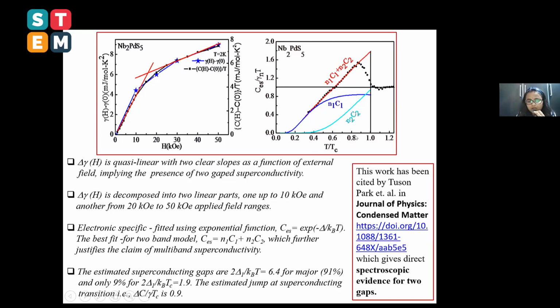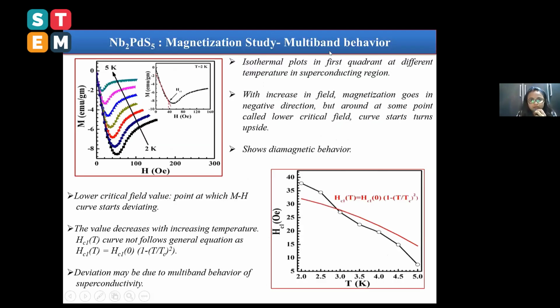And this work has been cited after this study. This work has been cited by Tuson Park et al. in the Journal of Physics: Condensed Matter. In this paper, they gave direct spectroscopic evidence for two-gap superconductivity. After this study as well, Nb2PdS5 fibers were grown by several groups, and they also showed from anisotropic measurements that Nb2PdS5 is a multiband superconductor. And from the magnetization study also we showed that this is multiband behavior.